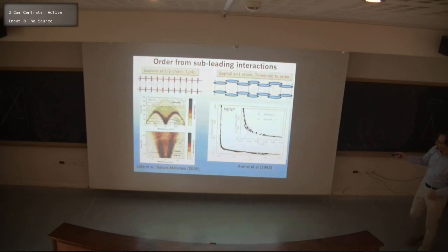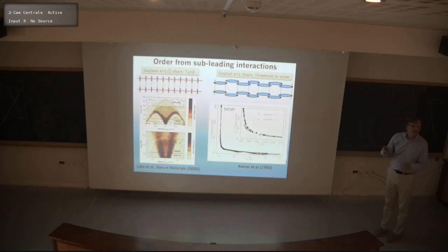This was done by a group at Gainesville, Florida. And you can see that they cool down to actually really, I think, certainly the millikelvin, maybe even microkelvin regime, and no order was developed. However, eventually there was this Curie tail, that's typically what people call it, and that basically was understood to result from defects in the sample.